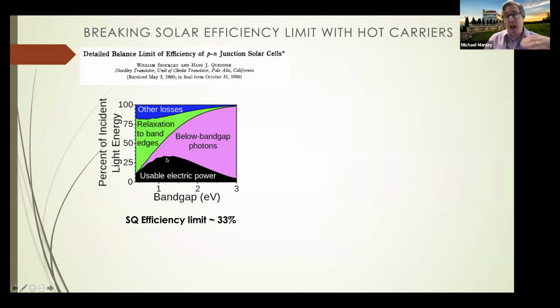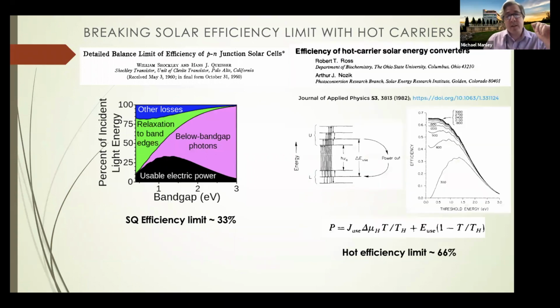Since then, people have been able to go beyond this, and they do it through complex architectures where you put a series of absorbers to collect more. But there is another way that people are looking at, and this gets to the hot carrier problem. You can make a more efficient solar cell if you can extract your charge carriers before they have a chance to lose their energy to heat. And if you do that, you get a different power output, and you will essentially double your efficiency. And some of you may recognize this extra term here.